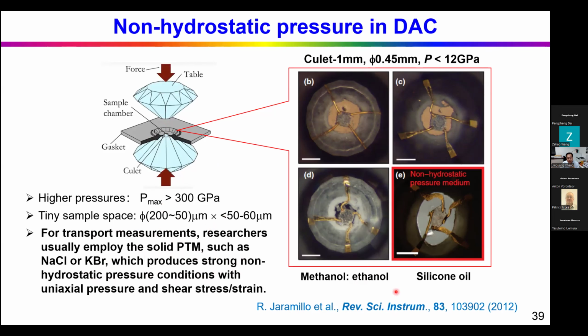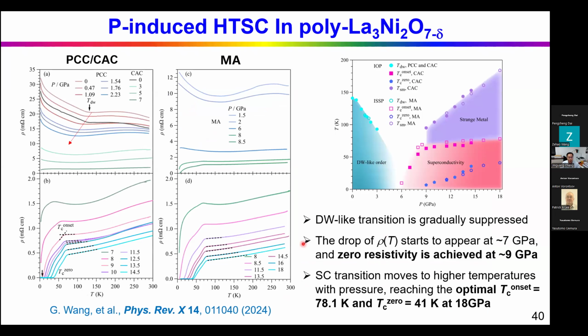In this paper, they put a chromium metal inside a diamond anvil cell. They use 2 different pressure media. One is a mixture of methanol and ethanol, another is silicone oil. Both are liquid, but the methanol-ethanol mixture has better hydrostaticity than the silicone oil. As you can see, under high pressures, the sample deformed significantly in the silicone oil because silicone oil will solidify under high pressures. Okay, I show our result.